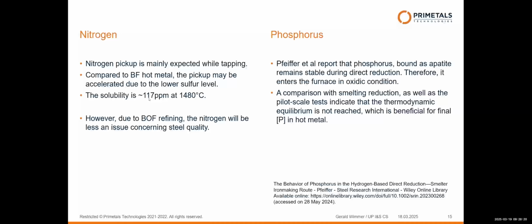And last point is phosphorus. For phosphorus, it depends a lot on the mineral fraction if reduction of phosphorus in the direct reduction plant takes place, or if these minerals are strong enough not to be reduced. And depending on this mineral fraction, it can be that we have similar phosphorus levels as on today's blast furnace, or slightly lower ones if the mineral fraction is too strong to be reduced by the direct reduction plant, which has, of course, a much lower reduction power than the blast furnace.